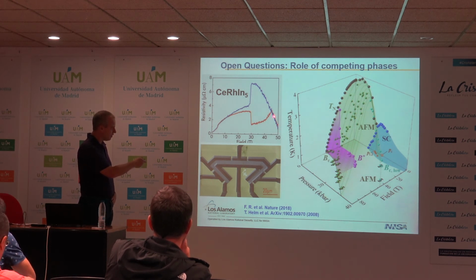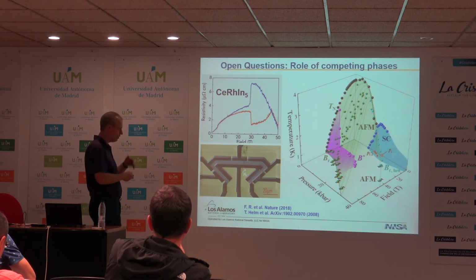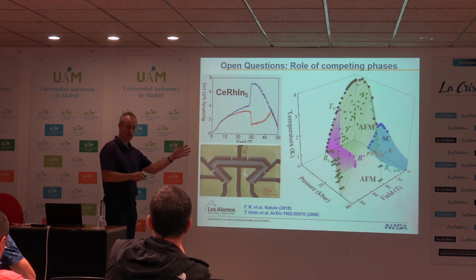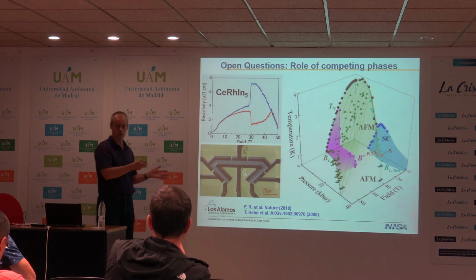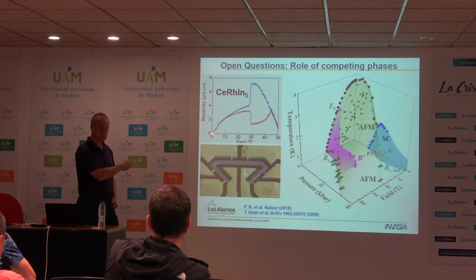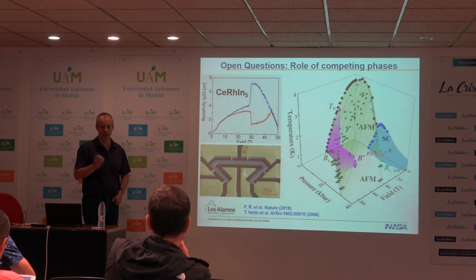So the suppression of the antiferromagnetic order happens here, and you're absolutely right. In fact, this resistivity reaches some sort of minimum here, just above 50 Tesla. We see this even when we have completely transverse magnetoresistance. With the transverse magnetoresistance, you would expect a huge orbital effect, and the fact that the resistivity matches this incredibly clean resistivity value here is not understood. And in fact, it dips down here and then shoots back up as you go towards 80 Tesla and reaches a resistivity value comparable to the resistivity at room temperature. So there's something very anomalous here that quite frankly I can't give a good explanation for.